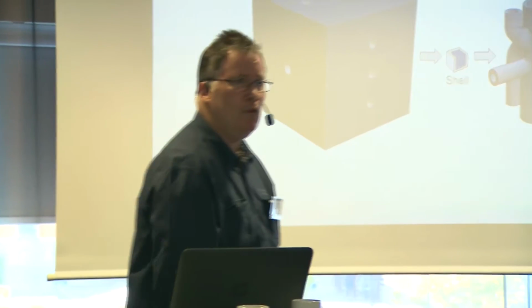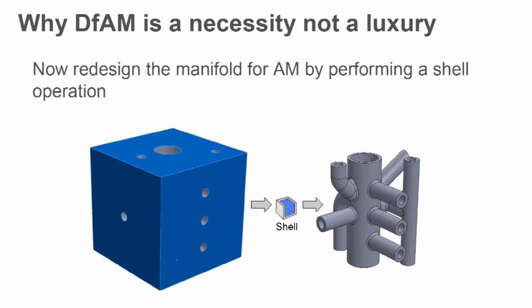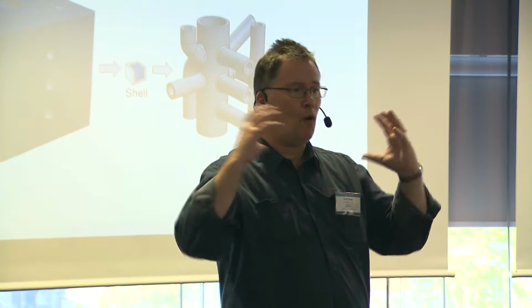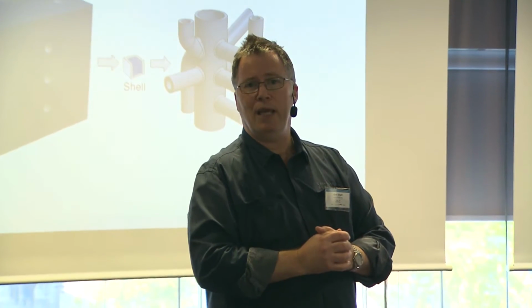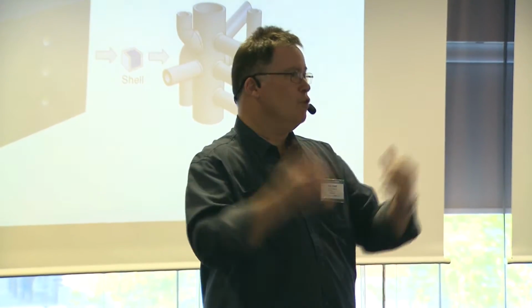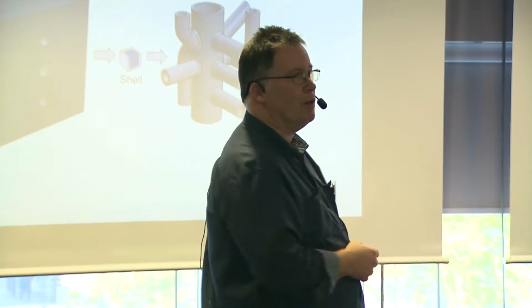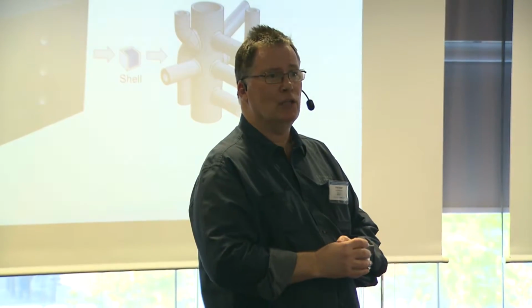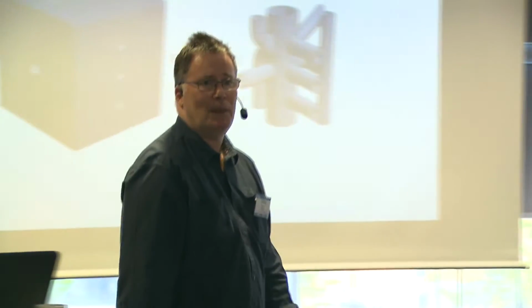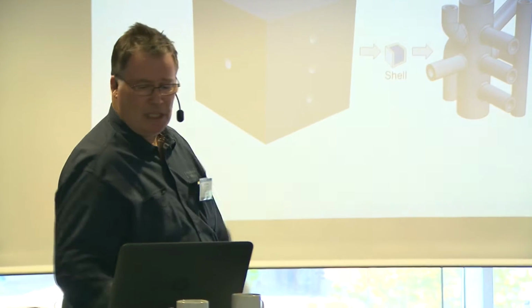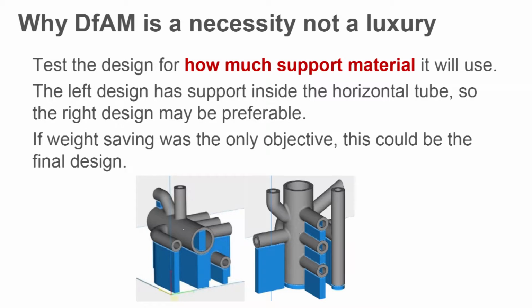In contrast, if you redesign the part, so we take the same part, I've just done a shell function in it, which you can do in pretty much any software to remove all of the material that's not doing anything necessary, and said I want a 2 millimeter wall thickness, and that's what you're left with. Perfectly functional design, it'll do the job. You can set the wall thickness based on the pressure. So when you run this through your 3D printing software, this is the support material that will be generated.